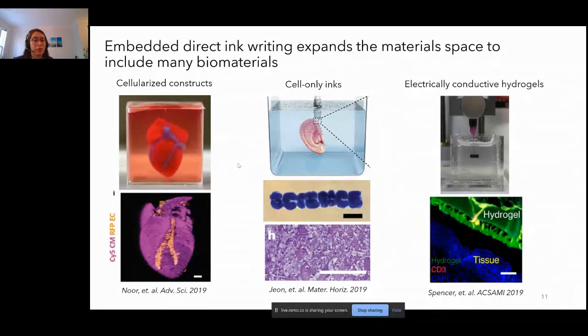People have also been able to print cell-only inks. Instead of having all these biopolymers available that scaffold the ink, they can print just cells, and those cells have been able to grow and develop tissues. And then you can also print functional materials, things like electrically conductive hydrogels, things that are at a low viscosity, where you've already tailored your ink to a certain functional property like electrical conductivity. You can still print that ink by using a support bath, because that support bath takes care of the rheology aspect.